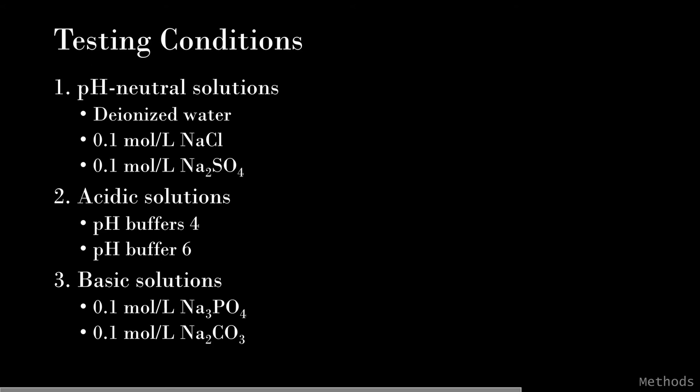The solutions tested include pH neutral solutions—deionized water, 0.1 mol/L sodium chloride, and 0.1 mol/L sodium sulfate; acidic solutions—pH 4 and pH 6 organic buffer solutions; and basic solutions—0.1 mol/L sodium phosphate and sodium carbonate, giving a pH from 10 to 11.